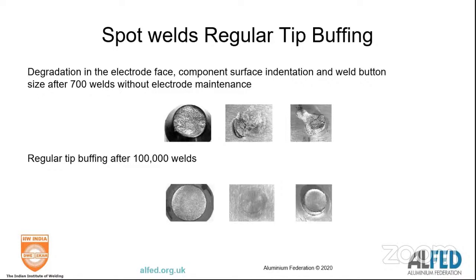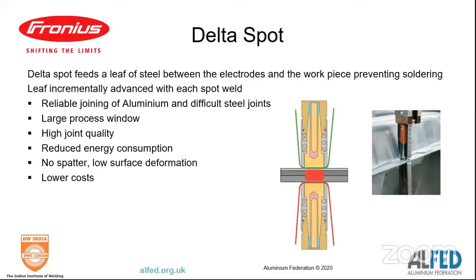There's another technique coming out which is called Delta Spot, developed by Fronius, and what they have is a very, very thin sheet of pure iron, and they pull it between the copper electrode and the aluminium to stop aluminium copper bonding, so they're welding through steel.